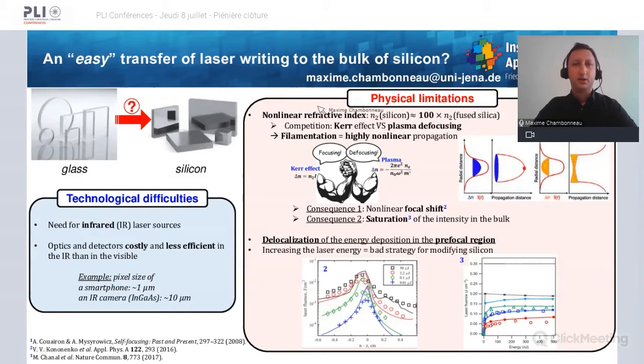Specifically, when you look at the nonlinear refractive index of silicon, it is about 100 times higher than the one of fused silica, for instance, meaning that at relatively modest peak power or input pulse energy, there will be a competition between Kerr effect on the one hand, which focuses the beam, and plasma defocusing on the other hand. In other words, we are in the filament regime, which is a highly nonlinear propagation regime. And this has two major consequences.